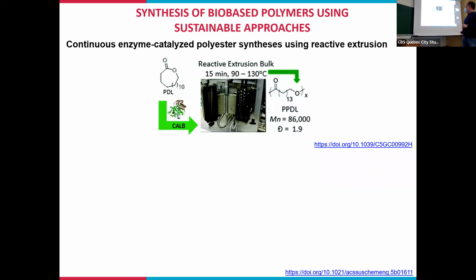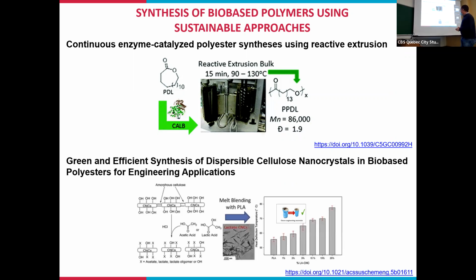By using reactive extrusion, we were able to get this polyester within 15 minutes. Just a very simple comparison, if you do the same in batch, it takes at least 2 days to get the final product. So that's a very beneficial effect - a simple process to boost the polymerization at the end.